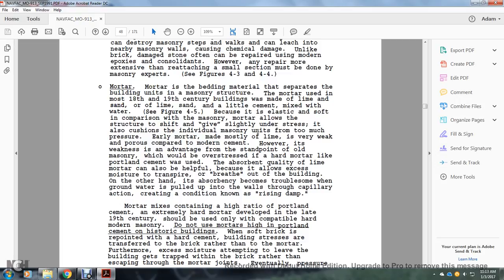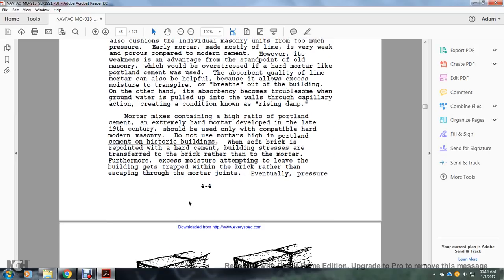It also cushions individual masonry units from too much pressure. Early mortar made mostly of lime was very weak and porous compared with modern cement. However, its weakness is an advantage from a structural standpoint. Old masonry would be overstressed by a hard mortar, such as Portland cement. The absorbent quality of the lime mortar was also helpful because it allowed excessive moisture to transpire, or breathe out of the building. On the other hand, its absorbency becomes troublesome when groundwater is pulled into the walls by capillary action, creating the condition of rising damp.